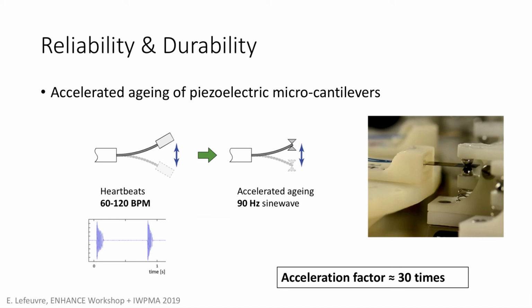So we just removed the proof mass, and we designed a system that reproduced the same deformed shape as the dynamic one with the mass. On the right, you have an image of this system. The cantilever is clamped here, and it's just gently held at its extremity here in order to enable the rotation of this extremity, and this reproduces perfectly the dynamic shape of the system. And if we consider a reasonable number of oscillations, we can say that we have approximately 30 times acceleration factor compared to real use.